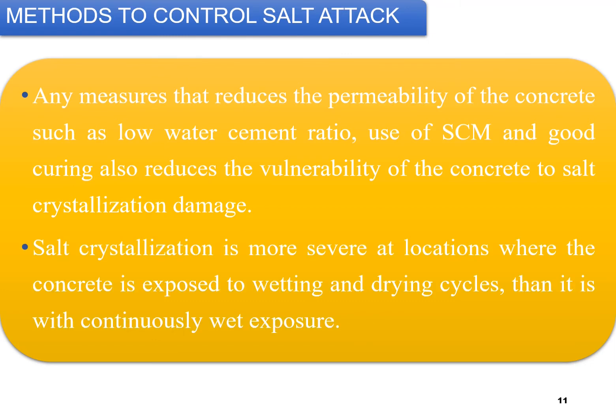Salt crystallization is more severe at locations where concrete is exposed to alternate wetting and drying cycles compared to continuously wet exposures. In sea conditions, particularly in tidal zones where alternate wetting and drying occurs due to high and low tides, you get salt and other conditions that promote the movement of salt crystals inside the concrete. Specifically for the tidal zone in a marine environment, extra precautions are taken by applying preventive coatings to restrict salt movement and eliminate damage due to salt crystallization.